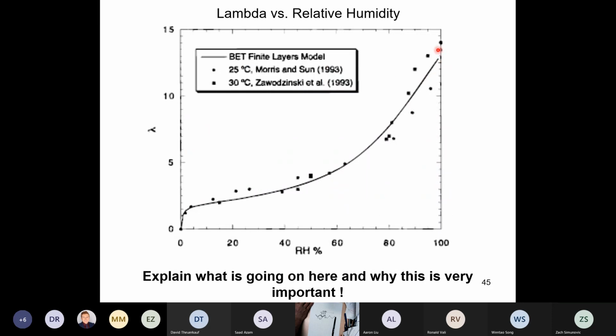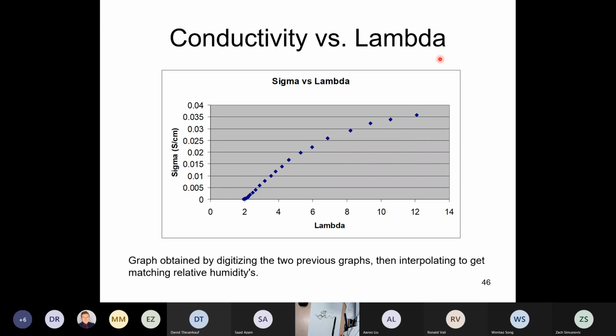So you'll have liquid water around when the relative humidity is 100%, and at that point lambda is about 13 or 14. So the maximum value of lambda that you can get is 13 or 14. That's what you would get if you took Nafion and put it in liquid water. So this turns out to be very important for fuel cell operation, and it's one of the things that you don't learn about if you just take a quick look at fuel cells. You say, oh, they're marvelous. But now you learn they're a little tricky to operate.